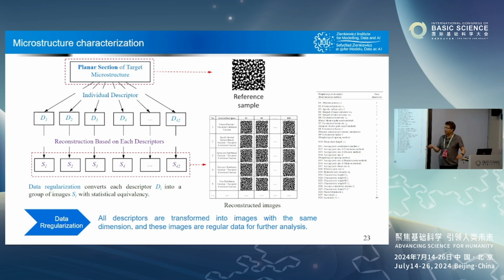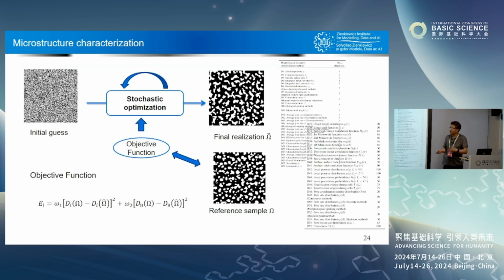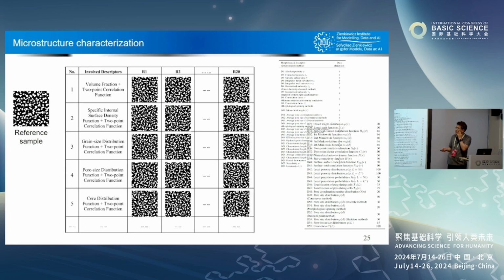So what we then did is we applied the same reconstruction algorithm, the same optimization technique, to build many sets of synthetic images. Each set corresponds to one descriptor. So the resulting data sets, each set of images captures the statistical information for one descriptor, which is of course linked to the original reference image. So again, it's biased because of that original reference image. To overcome that bias, you can pick multiple random images from different types of materials to make it more generic. But the logic is similar.